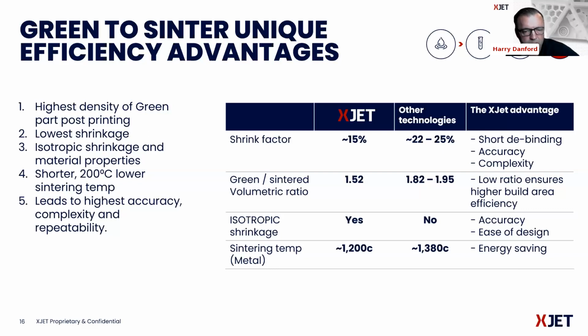In terms of sintering temperature, one of the real advantages here with the metal especially is that we can actually sinter at almost 200 degrees C lower, so we're not really approaching the melting point of the metal. And what this is really helpful for is in the sintering process, it really minimizes the slumping, the distortion, and some of the challenges that you have with respect to, again, metal injection molding and binder jetting applications.